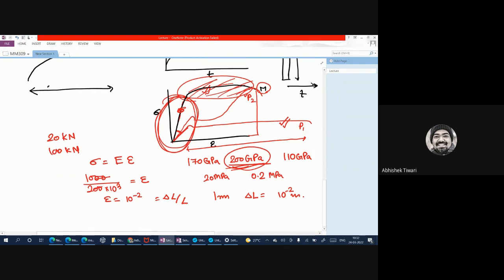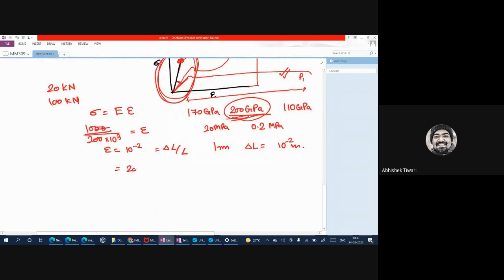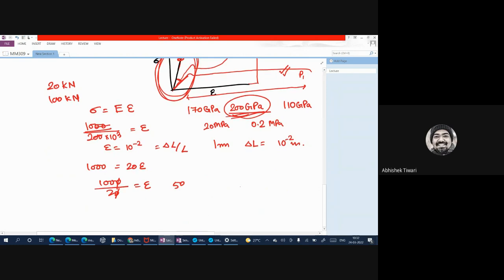Right? And now can you imagine, for the same amount of stress, if you apply it on a polymer where your elastic modulus is 20 megapascals only, and you're applying 1000 megapascals, so 1000 divided by 20, how much is the strain there? 50. So for a 1 meter long material, the delta L will be how much? 50. Do you see the difference? So this is why polymers have not yet replaced, and they can never replace, structural materials. You can't make pressure vessels, jet engines, railway wheels, or these kinds of things completely of polymers. You can't do that because the load bearing capacity, the structural capacity of polymers is not that high.